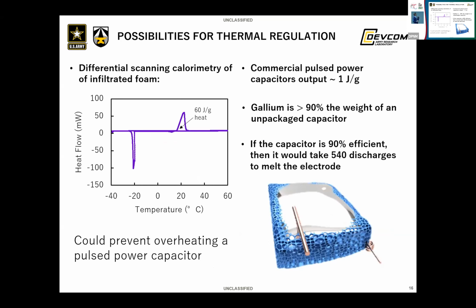So if you just do some hand-wavy back of the envelope calculations, a commercial pulse power capacitor is about 1 joule per gram. The gallium is 90% of the weight of an unpackaged capacitor. So if you had a 90% efficient energy storage process, you could have a bunch of discharges that would just walk the temperature up and then start getting absorbed in trying to change the phase of the liquid gallium.